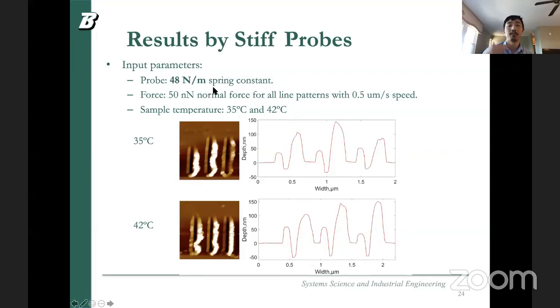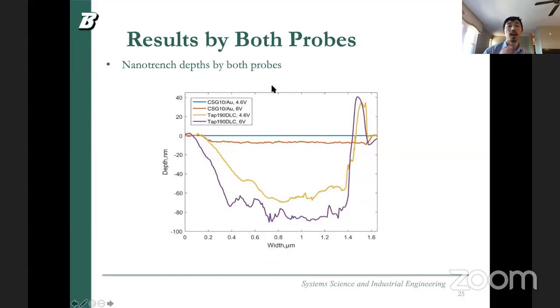If you use a very stiff probe with a 48 Newton per meter spring constant, same force, same 50 nanonewton, same speed, same temperature, we can see very, very deep structures over here. So this is 35, and 42 is even deeper. We plotted these results together. These two lines show the depth using the softer probes, and these very deep structures show using the TAP190 DLC probe, a very stiff probe. As you can see, with all the other machining speed, force, and the same conditions, the cantilever spring constant actually plays a very important role here.